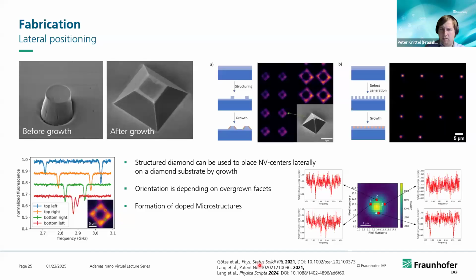In this publication in PSS, you actually find the coherence times. So this is the top one here. And they are, at least on what we expect to be in terms of P1 concentrations, at the limit of what could be achieved. One thing to mention here is that as these NVs are formed directly during the growth, the amount of NVs is not as high as if you're doing an additional irradiation or annealing treatment. If you do this on this pyramid, you will lose the preferential orientation, because then the vacancies will diffuse in all orientations. So for this oriented growth, you have to live with the typically ppb range of NV centers that are grown in during the CVD process.